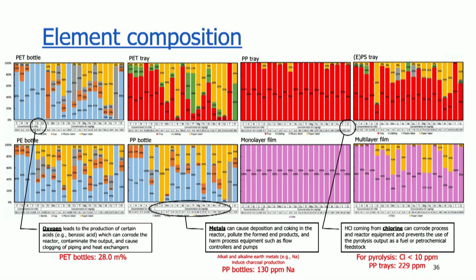A second thing that we analyzed were the metals, and here we see that certain waste streams also contain quite high levels of metals. For instance, the polypropylene bottles contain on average 130 ppm of sodium, which can induce coking and the production of charcoal during pyrolysis.